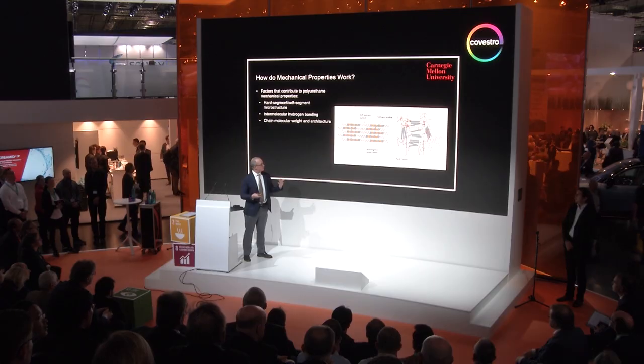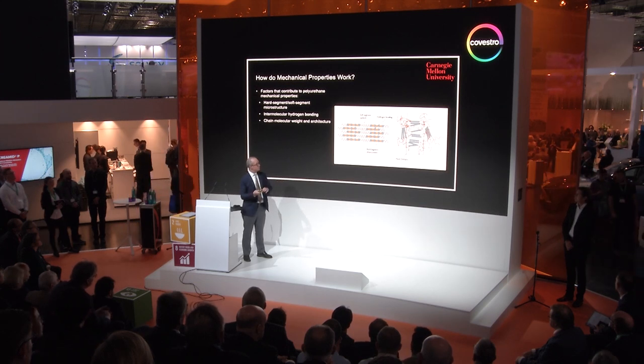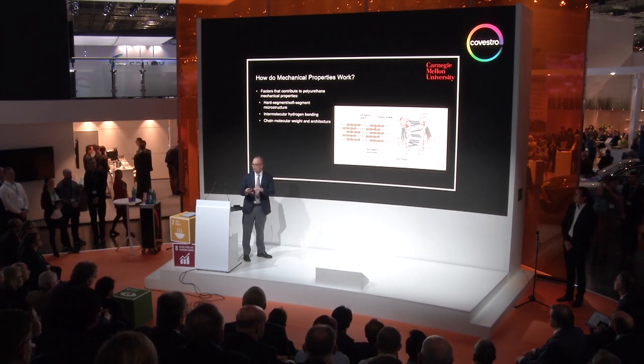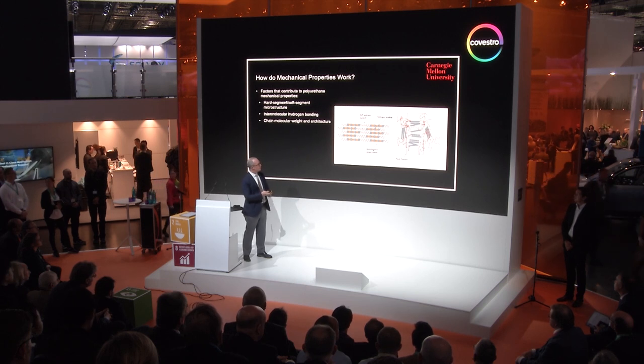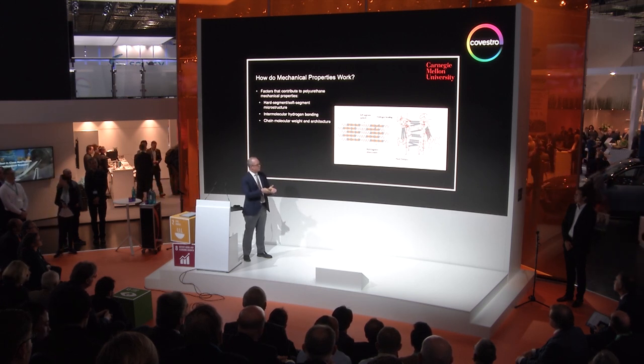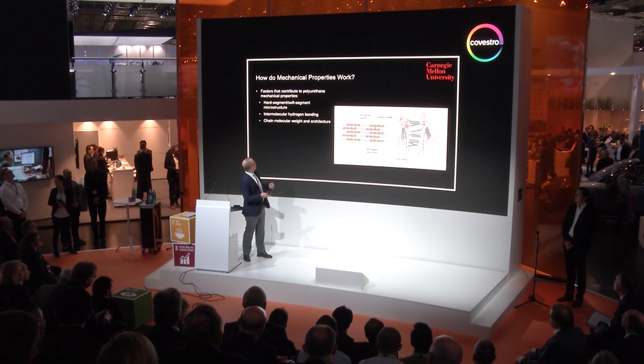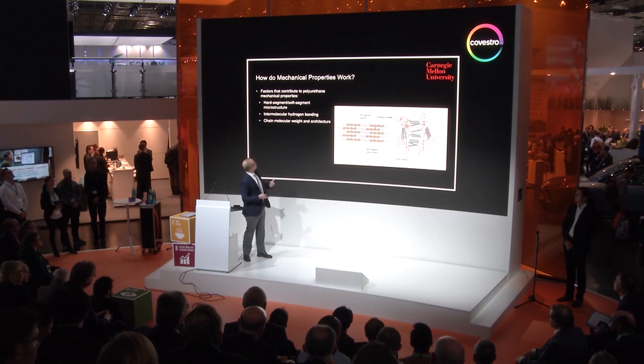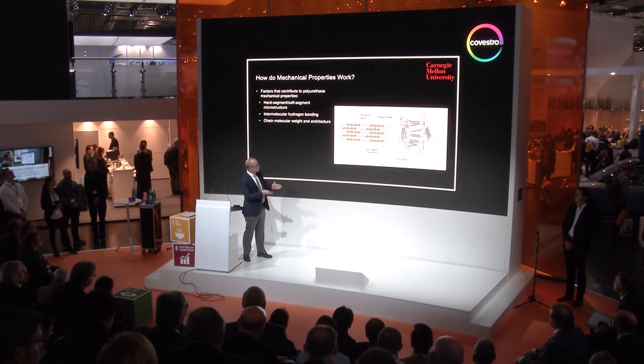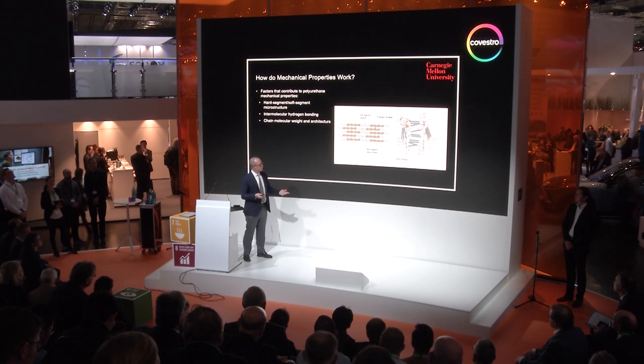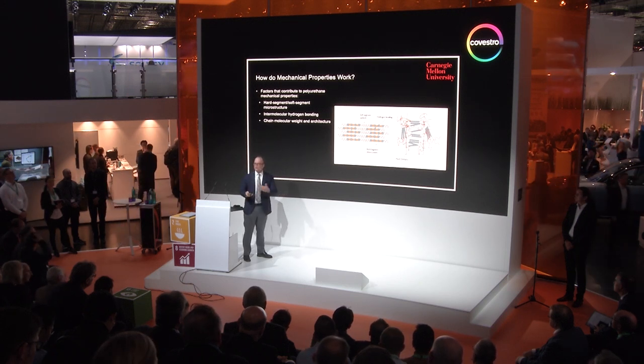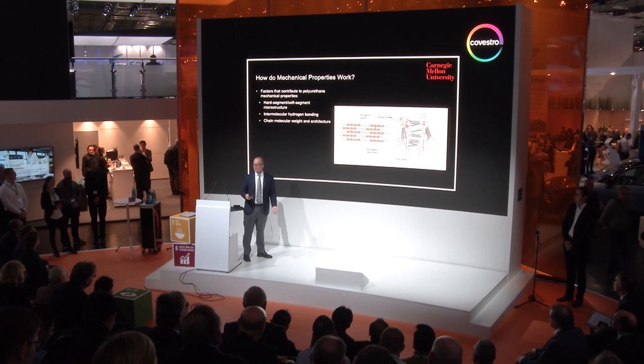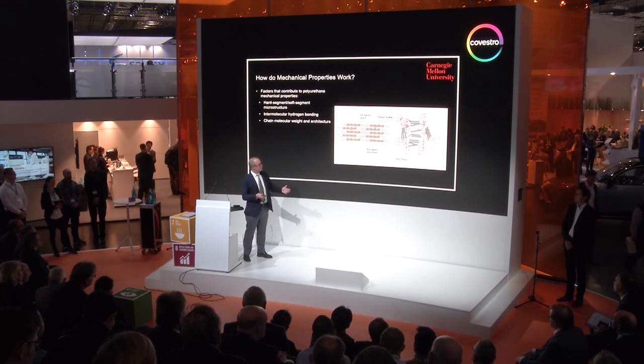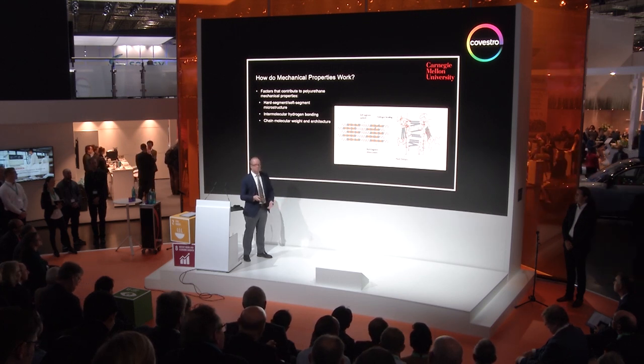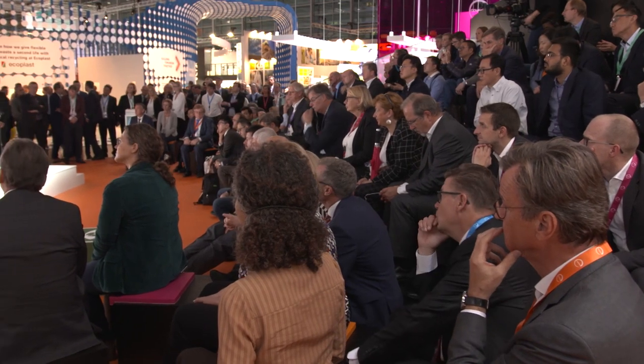But what we can do is take our knowledge of how this works, basically by saying the factors that really drive the mechanical responses are a combination of the interactions to form this microphase separated domain, the interactions between the chains, and also the chain architecture. Each one of these factors is something that we can model separately and then allow the algorithm to start to build a digital model of how the system works.